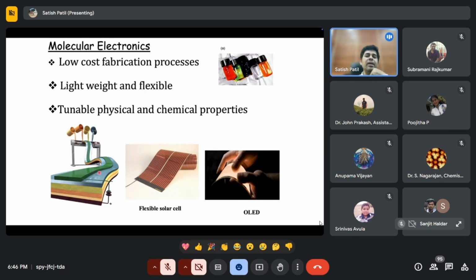Now, organic semiconductors, as I mentioned, if you compare with silicon, you have to convert raw sand of silicon into a device. You have to heat at very, very high temperature, and convert it into single crystalline silicon to make a sensible device. Whereas with organic semiconductors, you can make ink out of these materials, because organic molecules are soluble in common organic solvents. You can take any common solvent, depending upon the solubility of the organic semiconductor. You can make ink out of it.